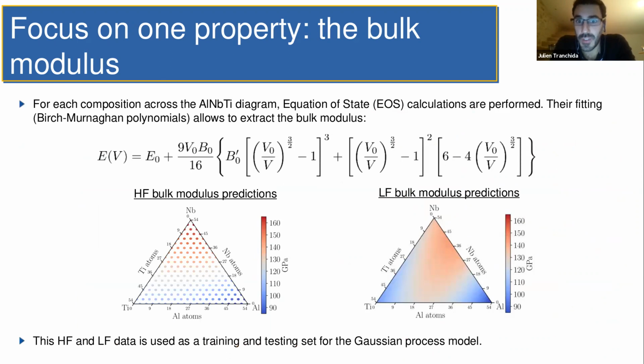Then we just do a fit with the Birch-Murnaghan equation of state. It's this equation of state here. If you take the second derivative at the minimum of energy of that equation, you end up with the bulk modulus. So that directly gives you the bulk modulus of your material. As you can see, you can apply exactly the same calculation for your DFT and MD calculation, and that gives you the typical predictions that I'm showing here. Of course, we're doing much fewer calculations for the high fidelity, first because it's quite expensive to run them, and second because it's also the idea of the work to show that with fewer high fidelity points than low fidelity ones, you can still get accurate results for the full composition space.